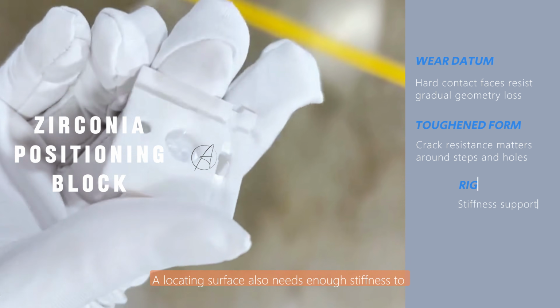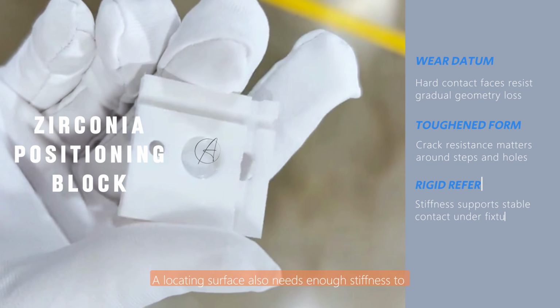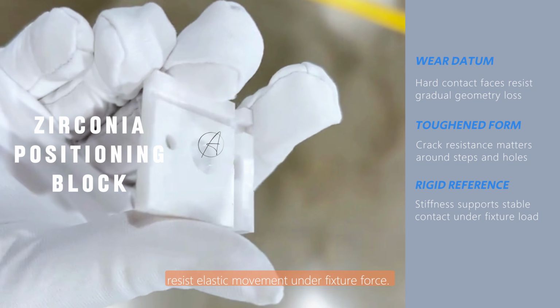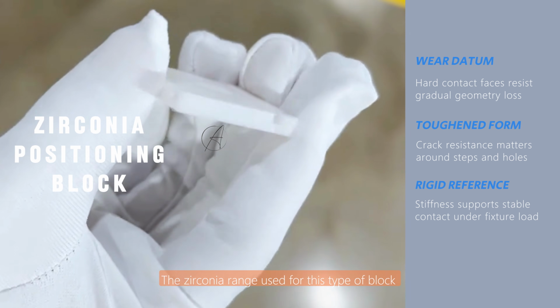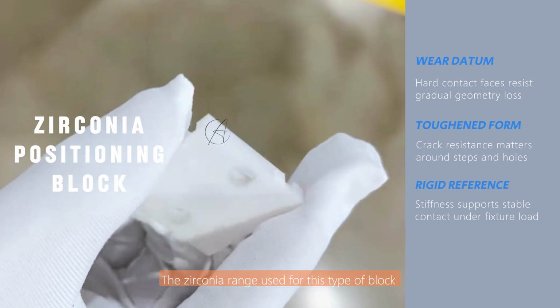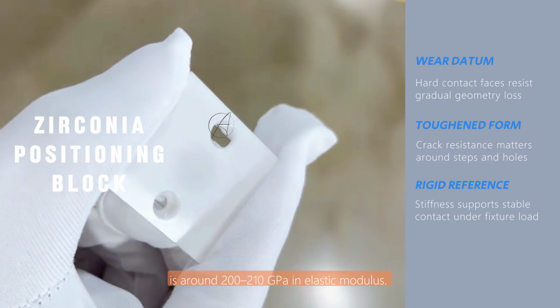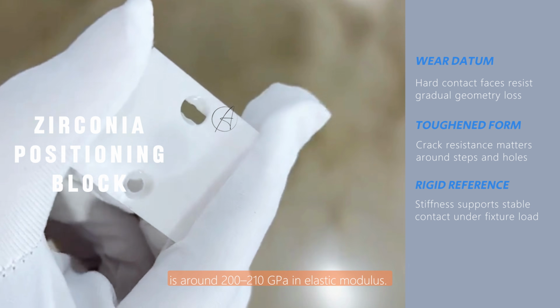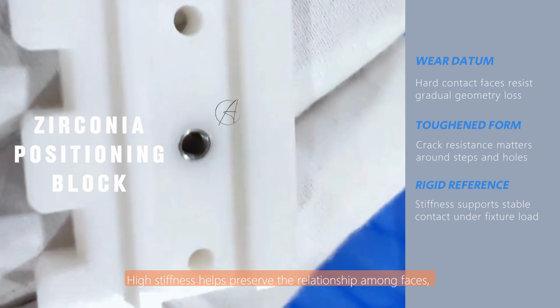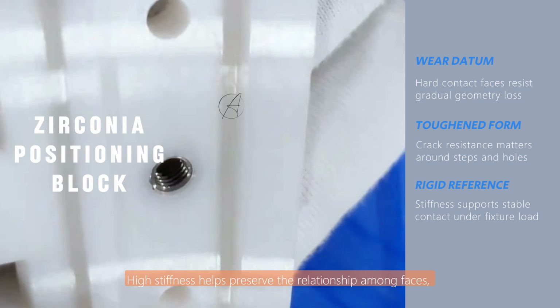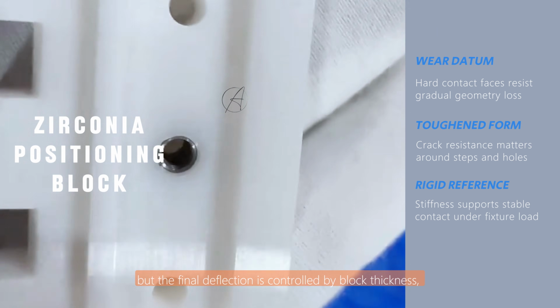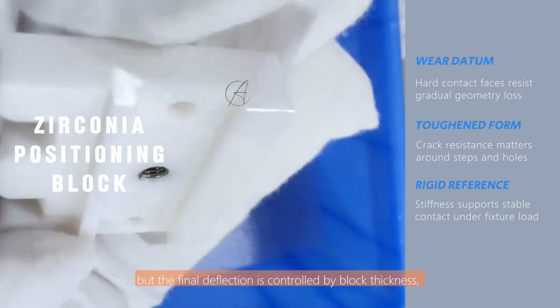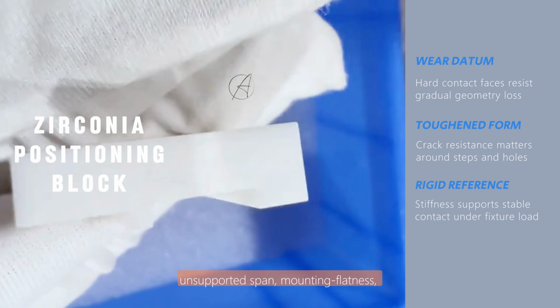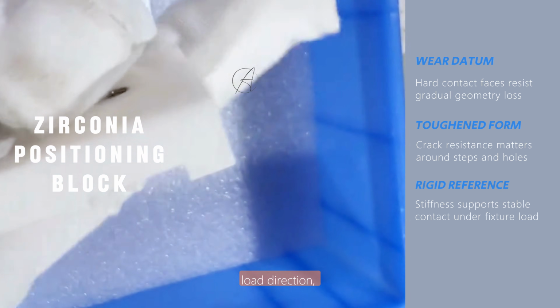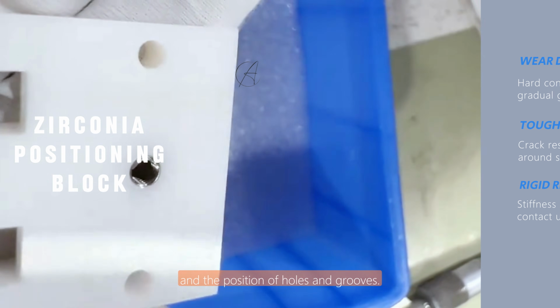A locating surface also needs enough stiffness to resist elastic movement under fixture force. The zirconia range used for this type of block is around 200 to 210 gigapascals in elastic modulus. High stiffness helps preserve the relationship among faces, but the final deflection is controlled by block thickness, unsupported span, mounting flatness, load direction, and the position of holes and grooves.